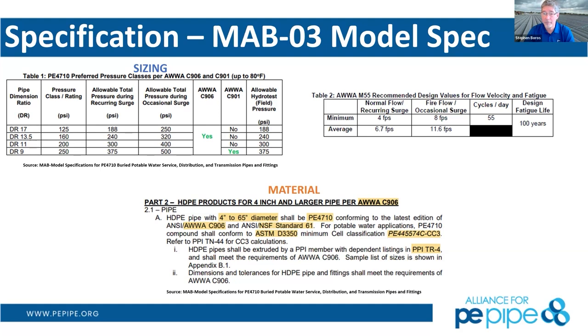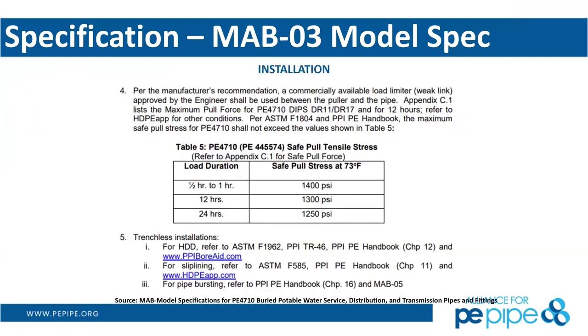If it happens 55 times a day plus, say for a force main, that's going to be millions of cycles over 100 years. Polyethylene has been tested for 10 million plus cycles with full cyclic fatigue from full pressure class to double the pressure class. Not just starting with a pressure class of say 125 and testing it at 80 psi like it's going to be used. We tested at 125 and then double that to 250 and go through millions of cycles to make sure ductile fatigue will not be an issue for polyethylene. Great question. Thank you.